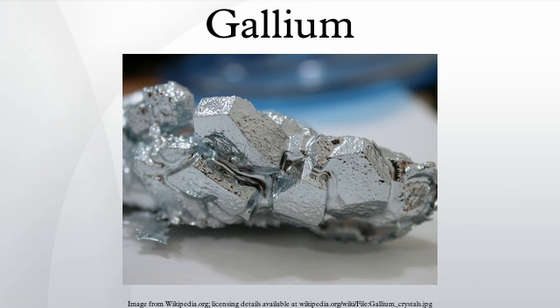When heated to a high temperature, gallium(III) halides react with elemental gallium to form the respective gallium(I) halides. For example, GaCl3 reacts with Ga to form GaCl: 2 Ga + GaCl3 → 3 GaCl. At lower temperatures, the equilibrium shifts toward the left and GaCl disproportionates back to elemental gallium and GaCl3. GaCl can also be made by the reaction of Ga with HCl at 950 degrees Celsius. It can then be condensed as a red solid.